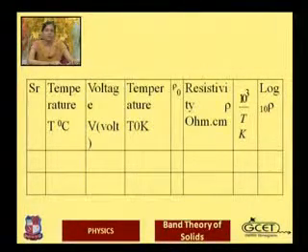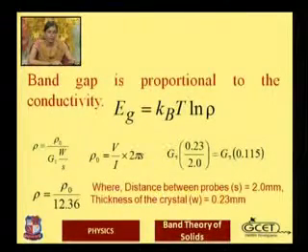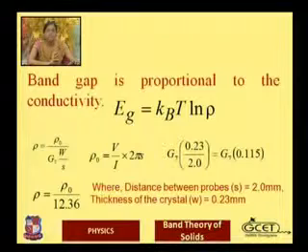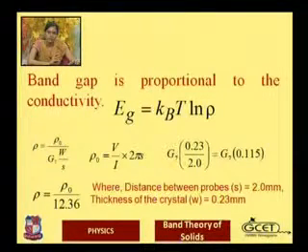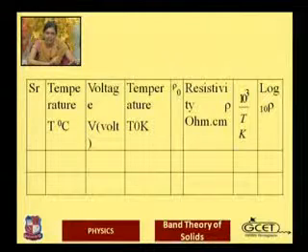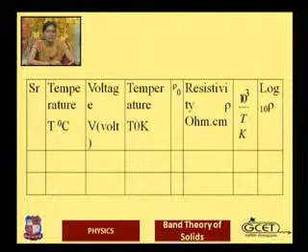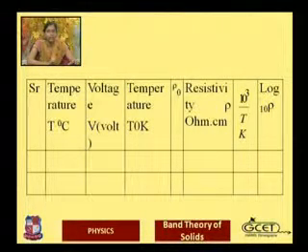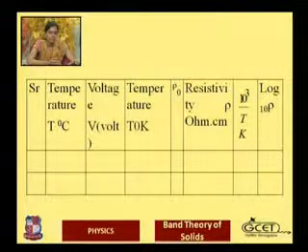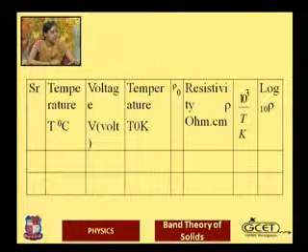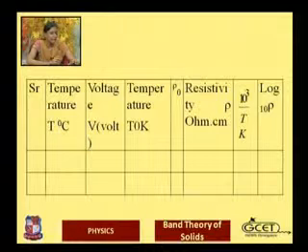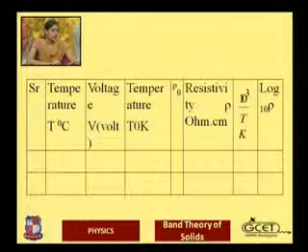In the observation table, three quantities vary: energy band gap, temperature, and resistivity ρ. Resistivity is determined from V/I, so keeping current constant at I = 3 mA, we increase temperature and measure the change in voltage across the specimen probes. We can then measure ρ₀, temperature in Celsius and Kelvin, resistivity in ohm·cm, and calculate log ρ (base 10) and 10³/T(K).